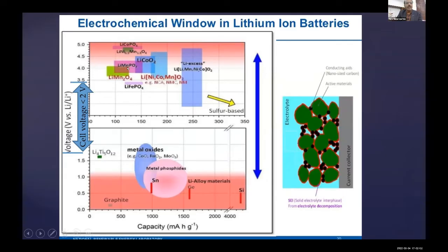If you see the lithium manganese phosphate, lithium nickel cobalt manganese oxide, lithium cobalt oxide, what you use on cell phone, as you go towards up, they're going into red region. There, even the solid electrolyte interface comes when you go to this region, even on cathode, which doesn't happen in conventional cathodes. But when you use lithium iron phosphate, which is now the key material for India,